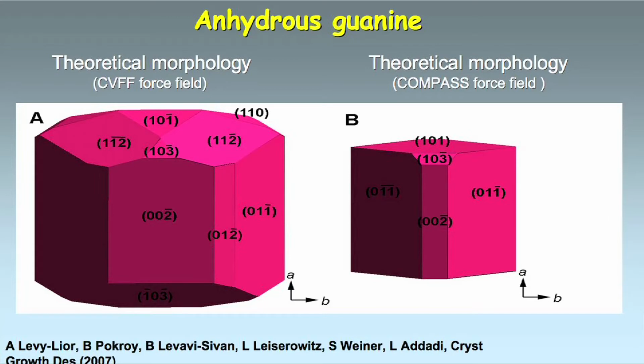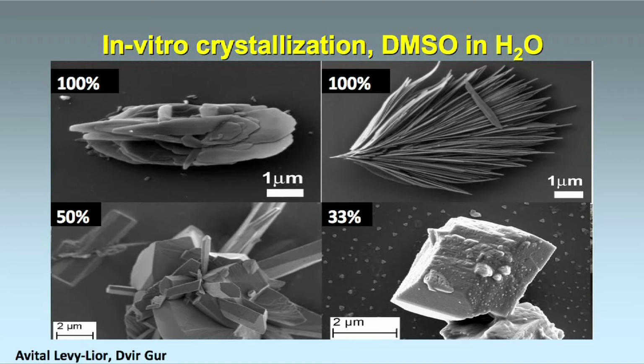This is just to show you that the theoretical morphology is not model dependent, that there are some small differences, but by and large, these crystals must be prisms. And then can we reproduce that? Well, actually, when Avital Lévy-Lior first succeeded in crystallizing these crystals, she did that from DMSO. And then we were kind of scratching our heads because they still were thin plates that developed a little bit thicker than the crystals in the fish, but they were thin plates. And it was only when we started to use water, that is in fact the medium where organisms make their crystals, that we did find the prismatic morphology.